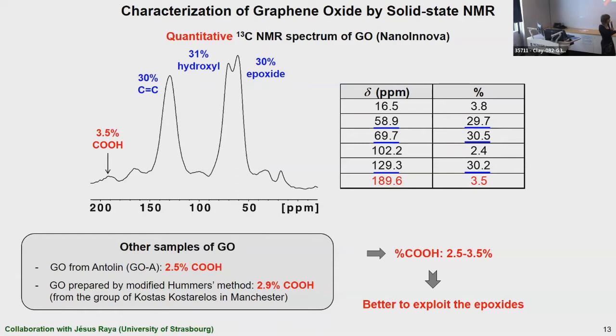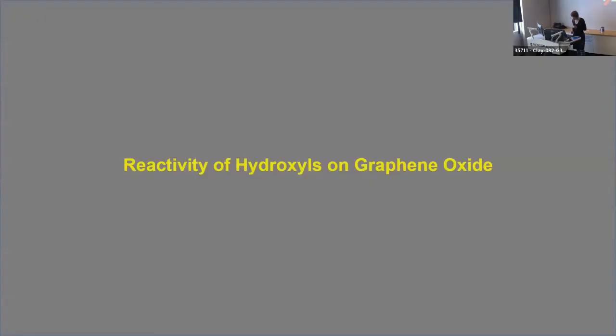And a graphene oxide prepared by the group of Kostas Kostarelos in Manchester, having 2.9% of carboxylic acid. So you see that among these different sources of graphene oxide, the percentage of carboxylic acids is in a range of 2.5 to 3.5%, which is very low, as expected. So to functionalize graphene oxide, it is much better to exploit the epoxides that are present in a larger amount on the surface of the material.